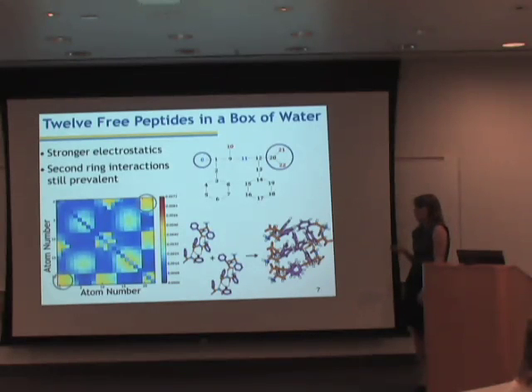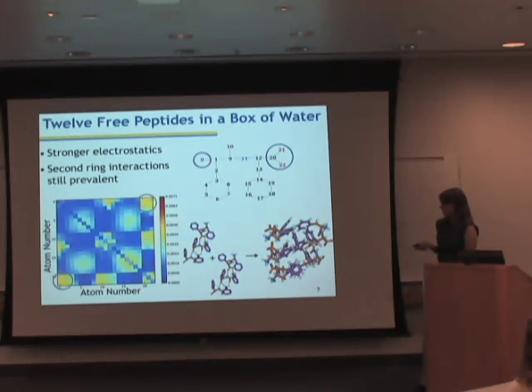When we looked through our videos of our simulation to find snapshots where these structures became apparent, we found that hydrophilic interactions, or charged end interactions, were most important in the formation of small oligomers, or the structures that form when 2 or 3 peptides come together. Looking at this trimer structure here, we see that it forms a ladder-like structure that is connected by these charged interactions, which are represented by the dotted lines,